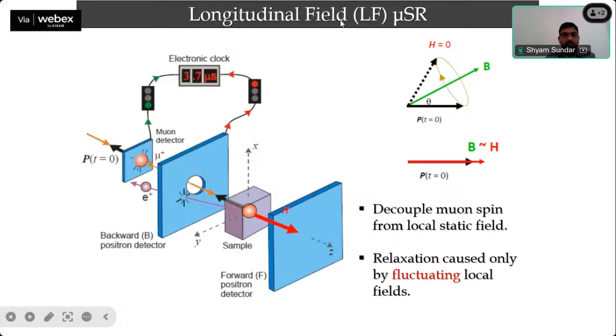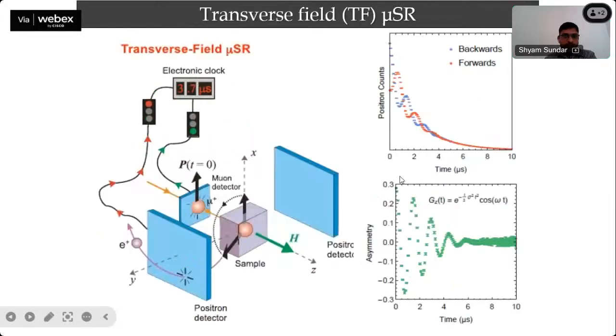But this longitudinal field measurement can tell us about the spin dynamics, because if you have spin fluctuations in your system, you can see if those spin fluctuations are of static or dynamic nature. You can decouple the muon spin from the local static field by increasing the magnetic field value, and you can see how much field you require to decouple the muon spin. So you can get the fluctuation rate and the order of magnitude of the magnetic field which is fluctuating in the system. Then you can also do the transverse field mu-SR measurement, where you apply the magnetic field in the perpendicular direction to the muon spin. So this experiment can be done in several different configurations.